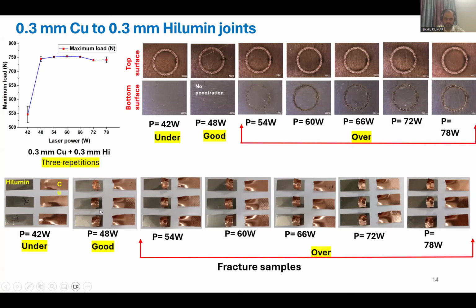In the same way we can pick what is the good weld. The first one is interfacial failure. Even though there is no bottom sheet penetration, we cannot say this is a good weld. It fulfills one criterion, no bottom sheet penetration, but not the other criterion, where the material should break. The second one fulfills the welding definition and also does not penetrate the bottom sheet. So the 48-watt power can be considered a good weld, and that's why you are getting very good strength for this one. The rest of the parameters can be considered overwelds because you are penetrating 100% of the bottom sheet. You can clearly see the laser impression on the bottom face. They are also breaking from the top surface, but this is not because of a good weld. It is because you are cutting, or creating a notch on the top surface because of the overheat.